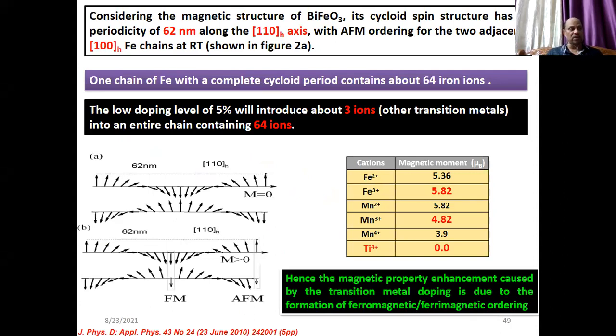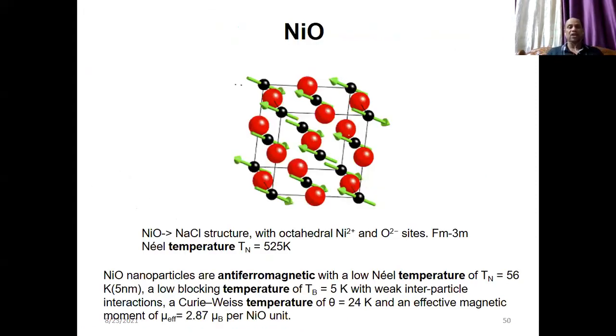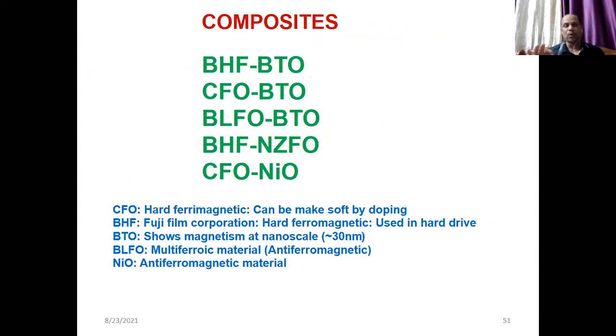And another one, barium, sorry, bismuth ferrite. It shows a spiral magnetic moment. Spiral magnetic moment in the sense that they are antiferromagnetic, but every 62 nanometers their direction changes, an interesting material. So if you reduce the size below 62 nanometers, you will find very good magnetic properties in bismuth ferrite. These are interesting phenomena, and nickel oxide is entirely an antiferromagnetic material, even above room temperature. So these are the interesting properties of these materials.